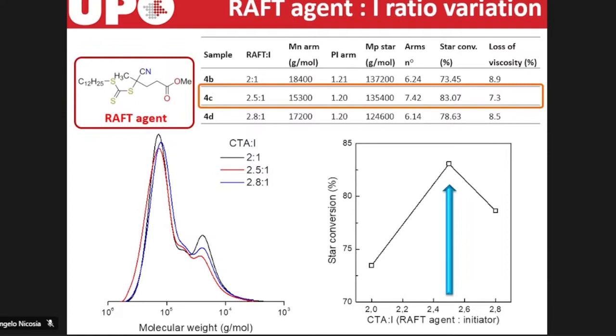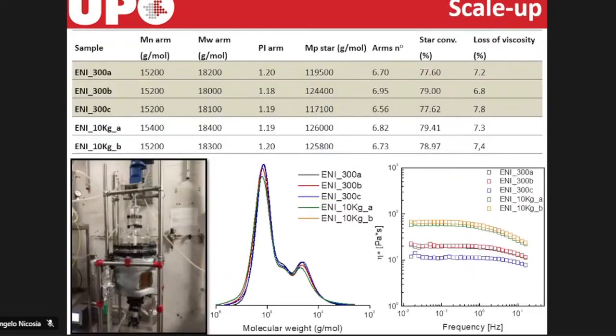So combining this experience, we tried in the ENI laboratories to make a scale-up of this reaction. So we realized 3 batches of about 300 grams and 2 batches of about 10 kilograms. And we observe that for an industrial application, this reaction has a great reproducibility.